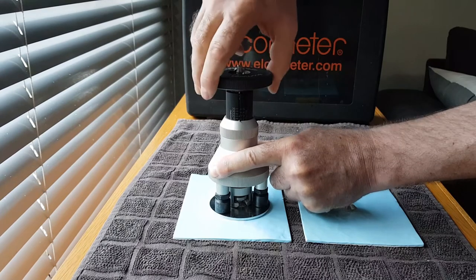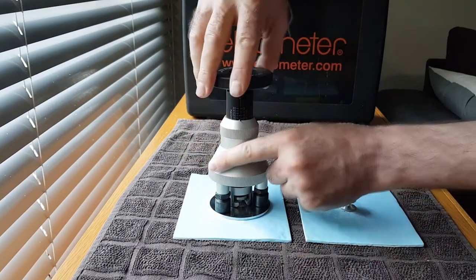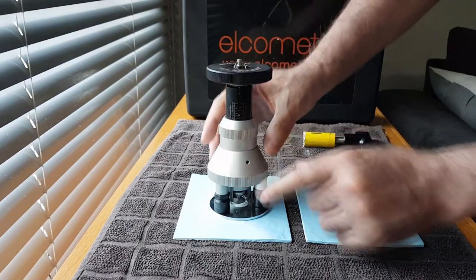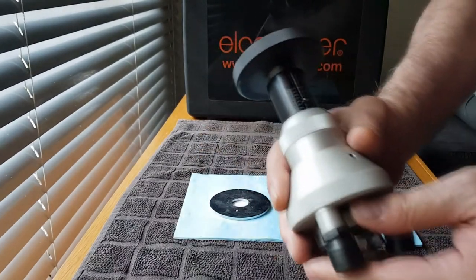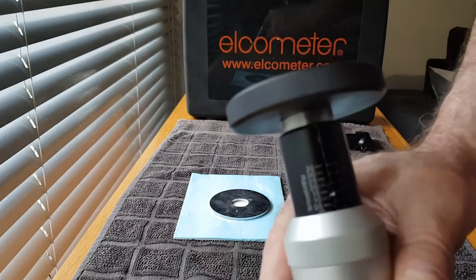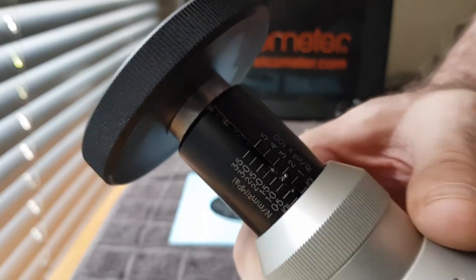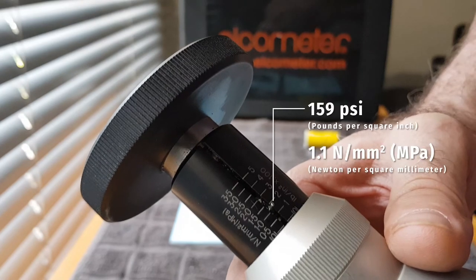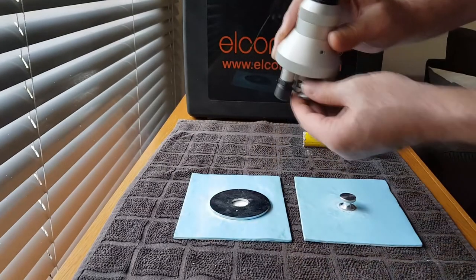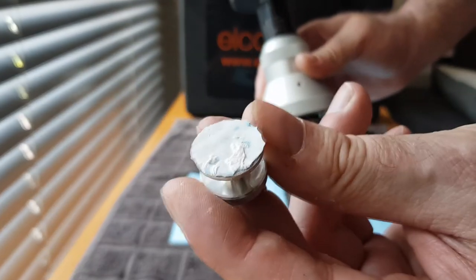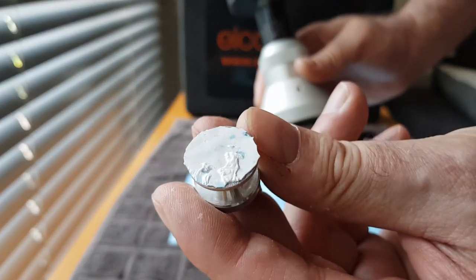You can hear the cracking, which is the fiberglass layers cracking loose and the fiberglass flow coat probably coming loose from the fiberglass itself. And so we've completed this test, and the reading is just over 1 newton per square millimeter. As you can see, it was not a paint failure. It is the white inner part of the fiberglass resin that broke. The blue is still on top, and it was the fiberglass resin that broke loose.